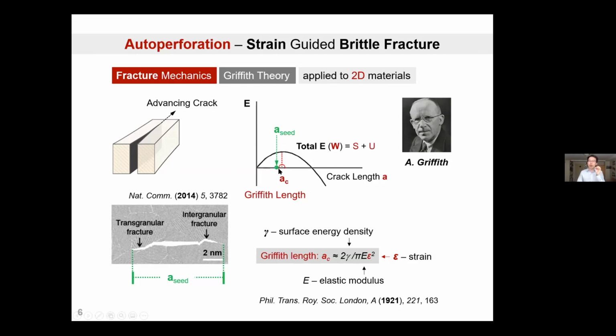Now consider a thought experiment. What would happen if I pull on this graphene a little bit? If I pull on this piece of graphene a little bit, then imagine that you're sitting at this crack tip: the strain energy is going to increase. According to this formula, your Griffith length is going to drop. So if your new Griffith length now suddenly sits on the left-hand side of the same seed crack length, the material will actually fracture. So by controlling strain, you can control whether, or the direction at which, a crack will propagate.